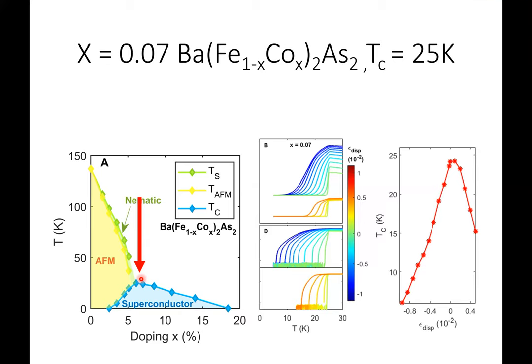Oh, no, I'm not talking about spin fluctuation. I'm talking about a static magnetic order. Because in all the doped samples that Jiehua looked at, there's always a static magnetic order. Static magnetic moment always decreases when superconductivity occurs. So it's directly competing with superconductivity. Whereas in the overdoped sample, there's very little static and long-range magnetic order. In the case of iron selenide, there's no static order at all, right? But spin fluctuations are there.